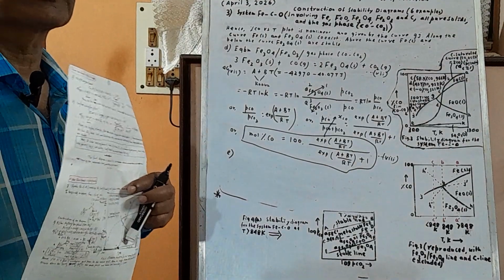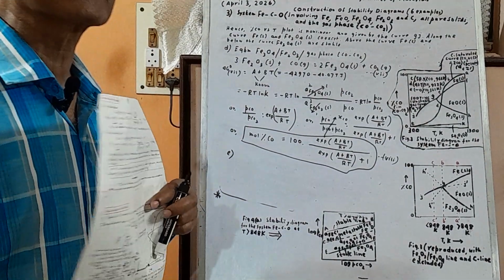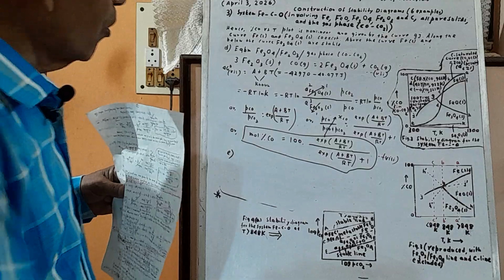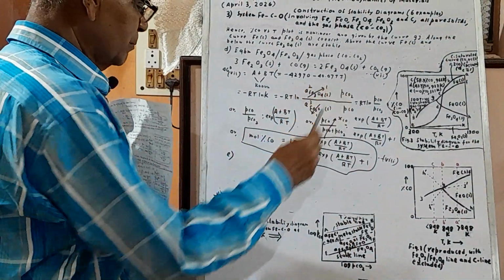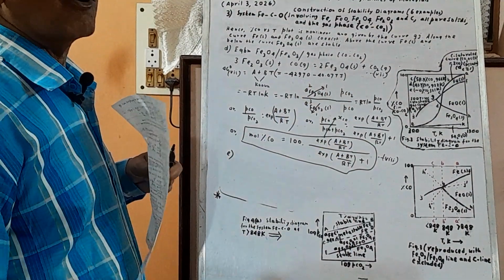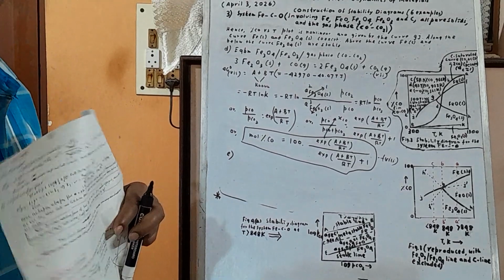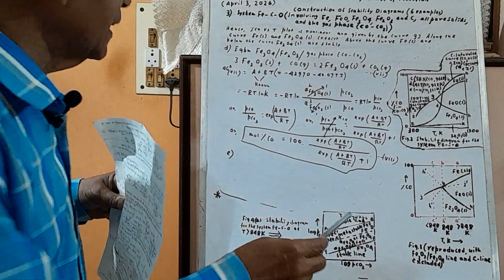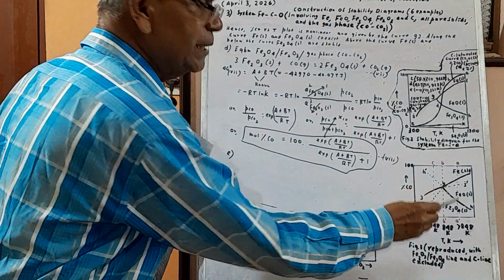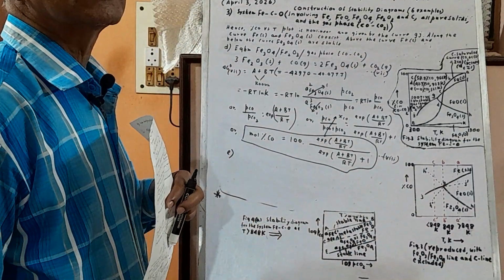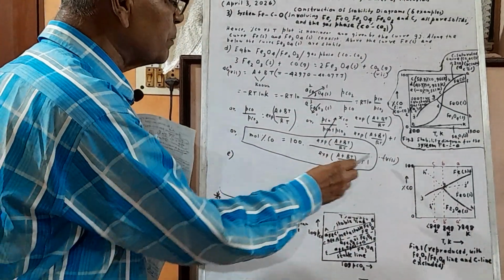The number of moles of gases is the same in all cases. So these curves are pressure independent, and in the expression there is no pressure term.